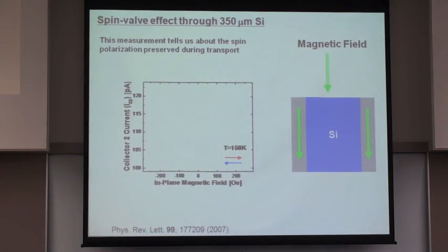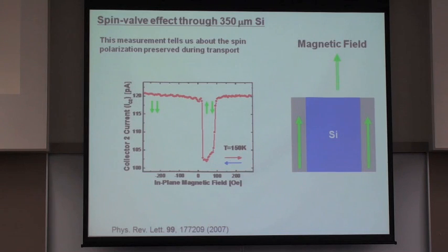Okay, so the simplest kind of measurement that we make is, as I described, just measuring the difference between injecting and detecting in a parallel and anti-parallel configuration. And we do this simply by using different ferromagnetic metals so that their coercive field is different. We sweep our magnetic field and we can obtain both a parallel orientation, in which case we have a relatively high second collector current, our spin signal. As we pass through zero magnetic field, though, one of the ferromagnets will orient its magnetization parallel to the magnetic field first, in which case we have an anti-parallel injector-detector configuration. Once again, enhanced inelastic scattering in the detector gives rise to a lower spin signal.